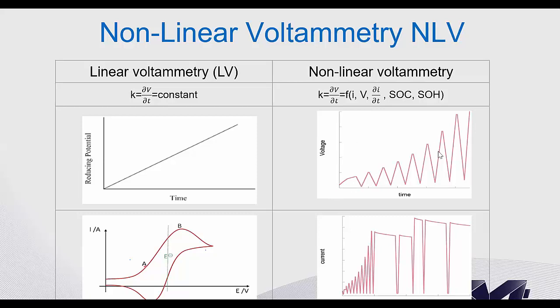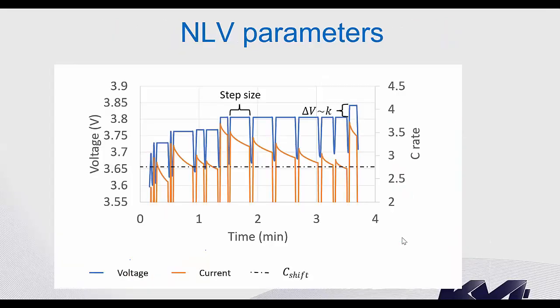So this is a profile of non-linear voltammetry. This is the voltage profile. You can see here we have a voltage plateau in a very short time. And there is that plateau. You see that the current is never constant. So the current is always increasing when we apply a voltage plateau, and then it decreases and so on. Now there are important parameters to what we call NLV, nonlinear voltammetry.